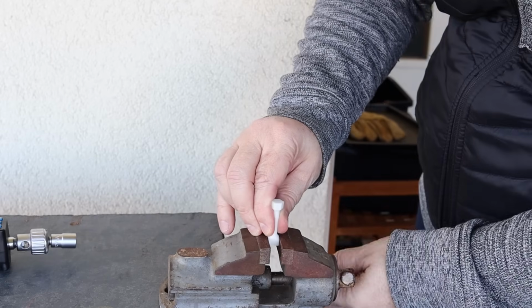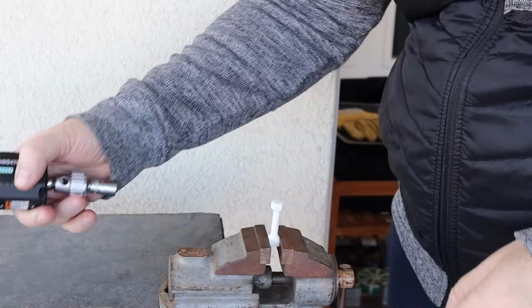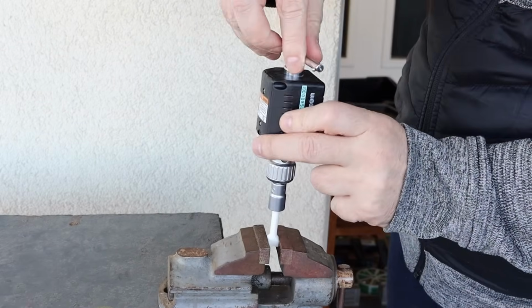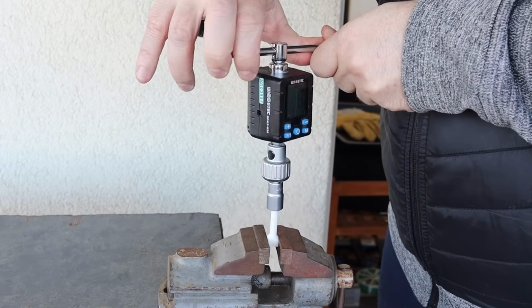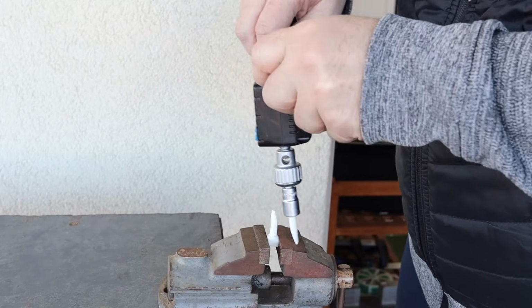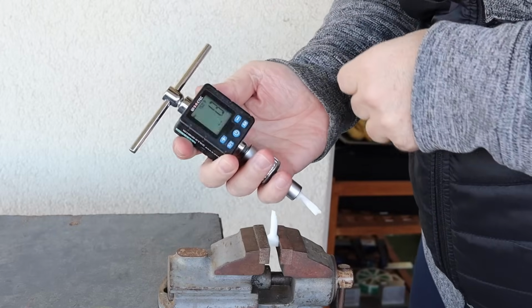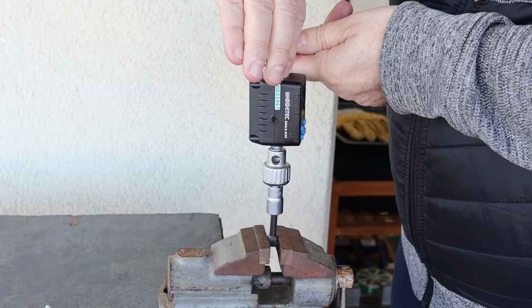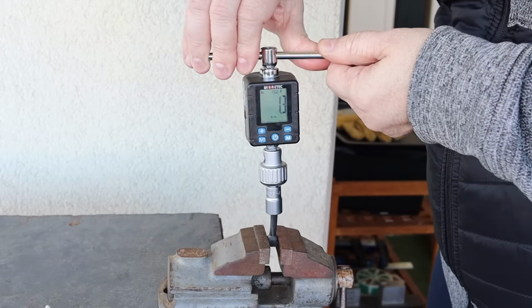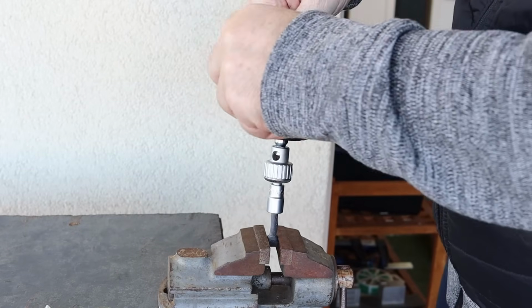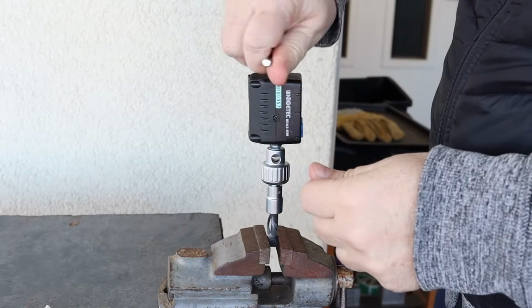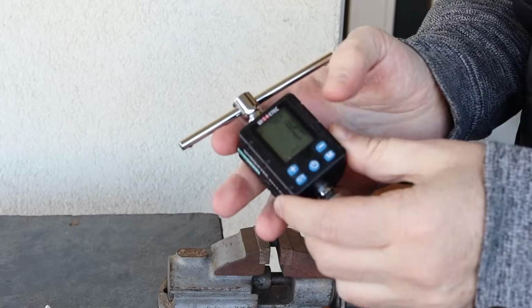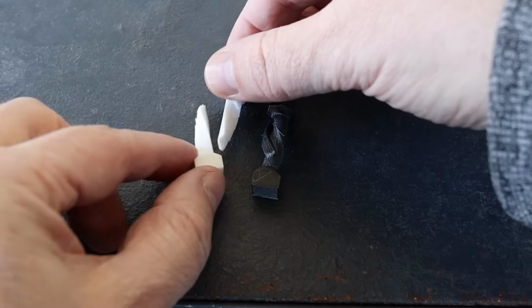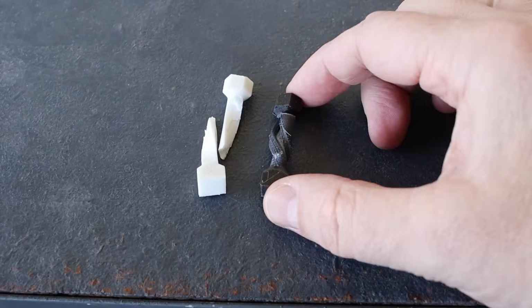And now the torque or twist test. I'm starting with the glass fiber filament. I'm measuring the load at a 90-degree angle and the maximal load, and this snapped very quickly at 1.3 Nm load. This is the carbon fiber version, and it is less brittle compared to the glass fiber, so I almost made a full rotation. And here you can see the deformation, it didn't break in two pieces.